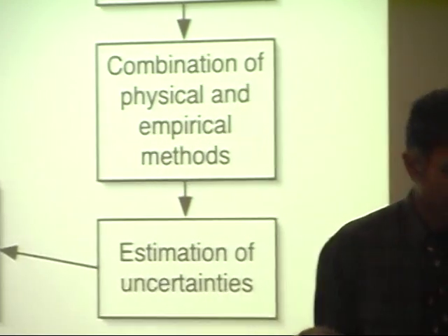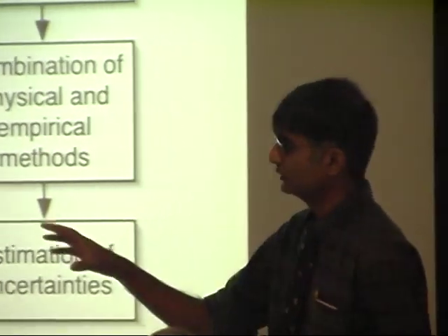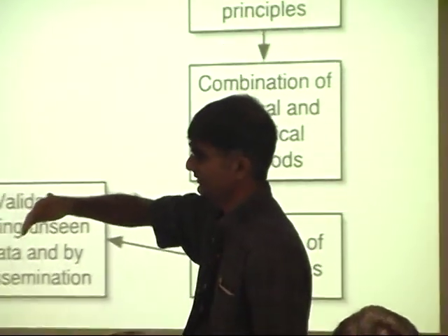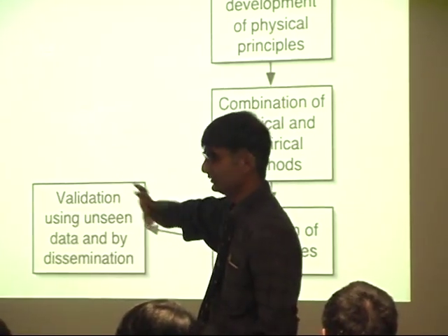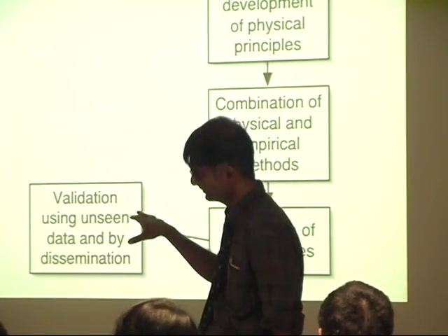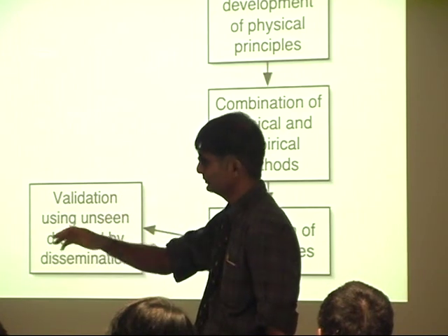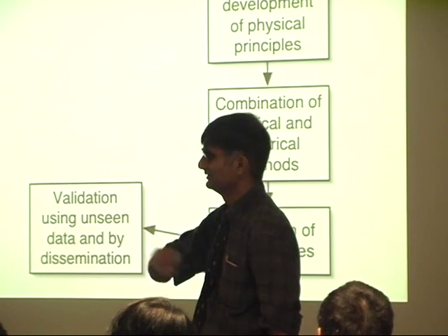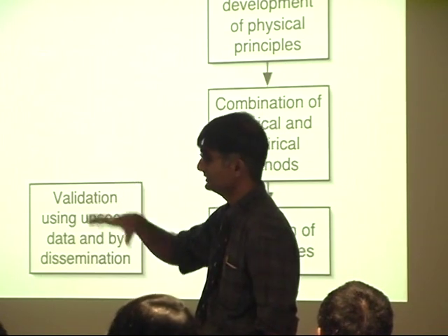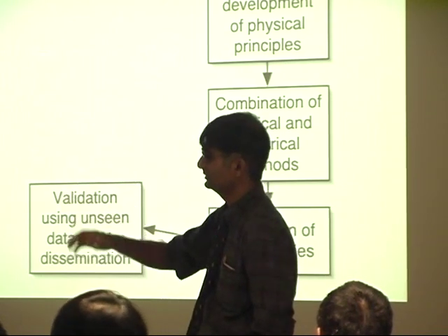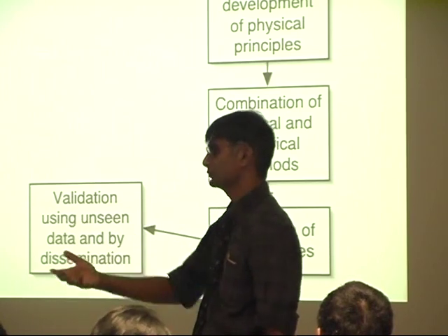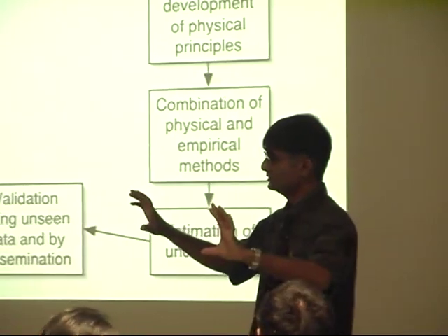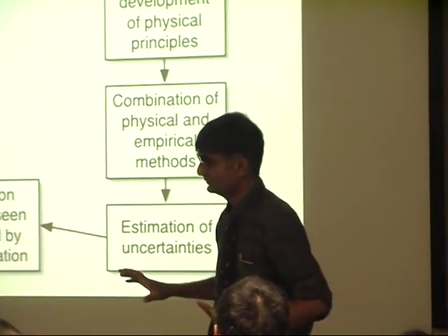Yes, I mean it is true that microstructure is a consequence of composition and heat treatment. So if you include composition and heat treatment, you can leave out the microstructure. But supposing you want to know whether acicular ferrite is really good, then you can put that in as a variable and discover the effect of acicular ferrite on the property. So it depends what you want to do. You're absolutely right. Once you've got composition and processing, everything is defined.